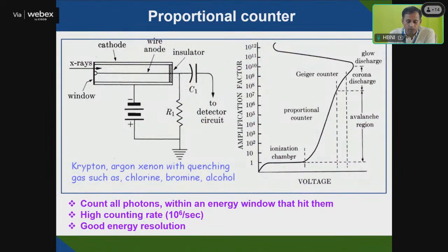And if you see the commonly used GM counter and the proportional detector, here it counts all photons within the energy. Your X-ray is coming here, and this falls on this window. Inside are krypton, argon, xenon with a quenching gas, some of these gas molecules. The X-ray coming from here will ionize them, and depending upon that ionization and the amplification factor, you can get an ionizing chamber, proportional counter, or GM counter. So mostly in X-ray diffraction we use either the proportional or GM counter.